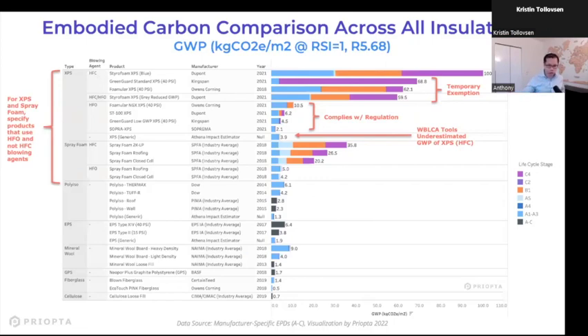So when you think about refrigerants used in your mechanical systems, they actually have a very high global warming potential, meaning that if any of those gases leaked out from your mechanical systems or from your insulation as a blowing agent, those gases are thousands of times more impactful than CO2. And so even small releases of these gases have a huge impact from a climate change perspective. Historically, all XPS and all spray foam insulation in North America was produced using HFC. And we had actually underestimated the scale of these emissions in many of the LCA software tools that the building industry was using previously. For example, the conventional XPS product that most people were using was probably around 100 kilograms of CO2 per meter squared at RSI equal to 1, which is about 1 inch of insulation for XPS, a little bit more. So that's very significant, 100 kilograms of CO2 per meter squared for every inch of insulation.